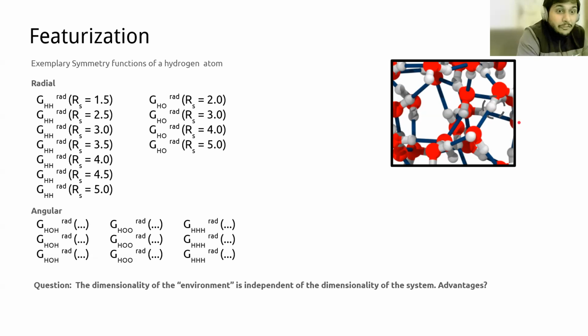Now you have this set for this, and you start computing these radial symmetry functions. This is going to probe the number of atoms closely around this particular value. This will probe something around this value, this, and this, and so on. So within a radius, this will really tell you what exactly is the density distribution of all the other atoms for this given structure, right?